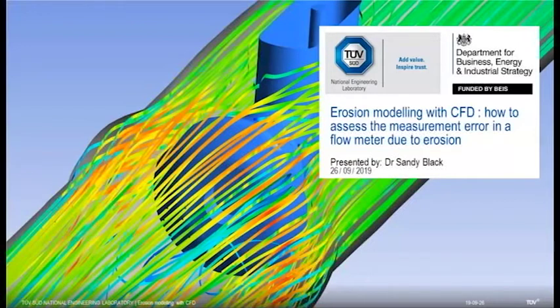There's a few other questions as well. One is just a general one. What would be the best approach to mitigate erosion in a piping system? So this is essentially a balance between mitigating erosion whilst also ensuring that there's sufficient pressure to drive the flow to its desired location. So the size and the shape of piping components in combination with the sand particle size and the fluid properties such as the density and the viscosity obviously influence the amount of erosion caused by sand. So you would probably select pipe diameters that are as large as possible, so you'd keep the flow rates low. We don't want them too low, because you may not be able to have sufficient pressure to drive the flow.